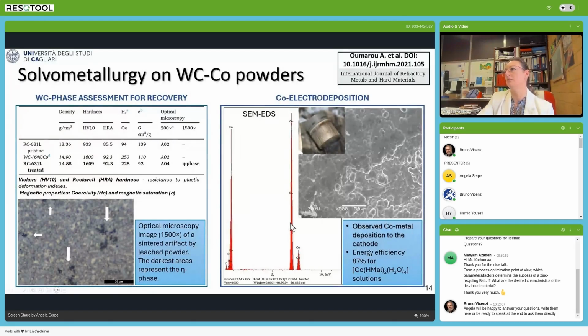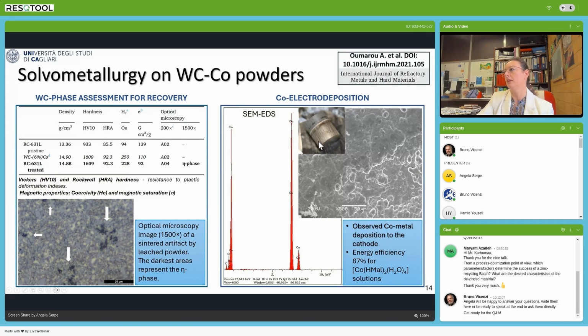from the solution, because we were able to isolate the cobalt compounds, the cobalt complex obtained from the reaction of cobalt with maleic acid. The complex can be isolated in the solid state and then dissolved in water, and we can recover the cobalt as cobalt metal directly on a cobalt cathode. So this is an example of how we can play on the coordination chemistry of the organic acids towards cobalt to promote selective leaching of tungsten carbide cobalt mixtures, avoiding oxidation phenomena in these cases by using solvometallurgy instead of water as the main solvent.